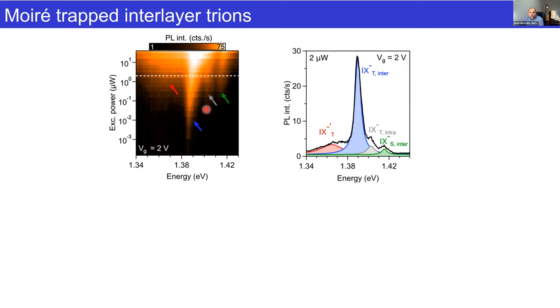And so line cut up here, at this excitation power where the white line is, gives us a spectrum that looks something like this. And here we see essentially four different species of interlayer excitons. I won't describe this red one that we don't understand very well, and I don't think anybody understands very well. It's been observed in other samples as well, in monolayer samples, perhaps related to plasmon or Auger processes.